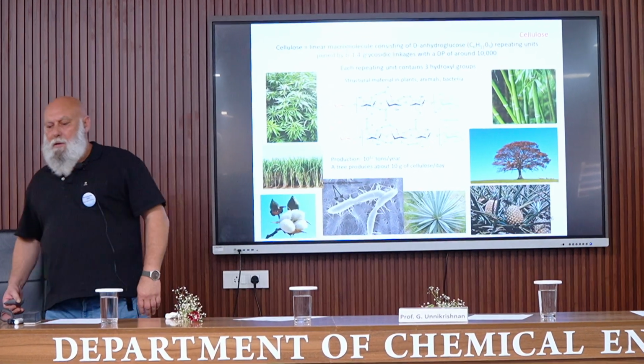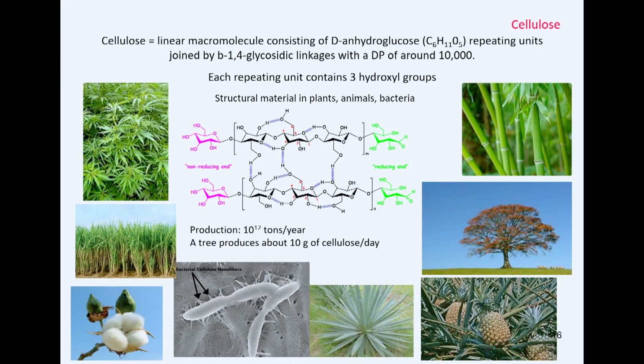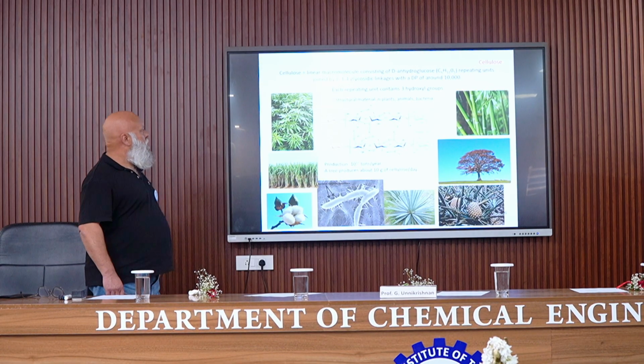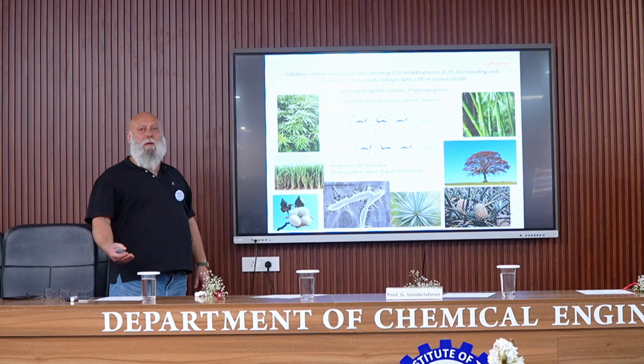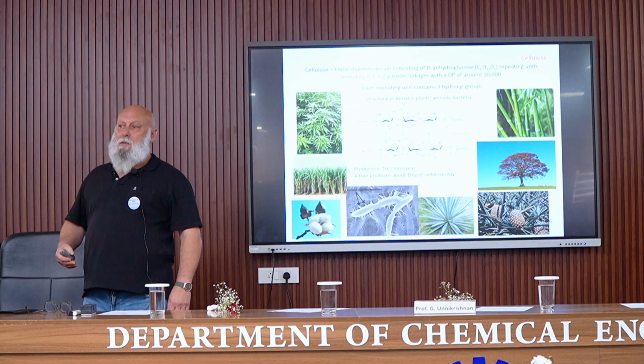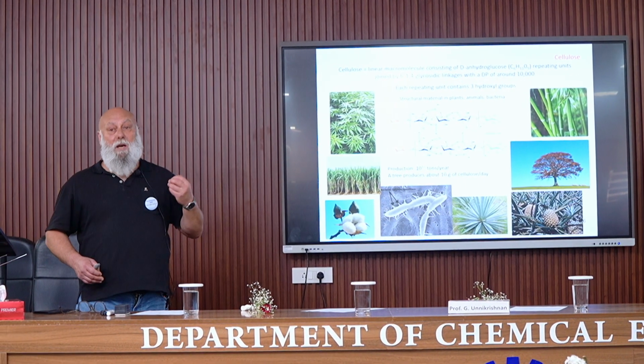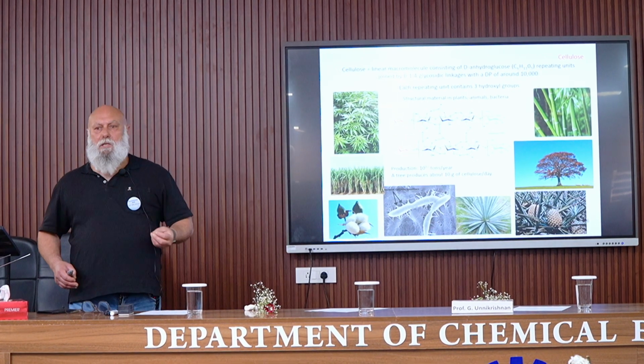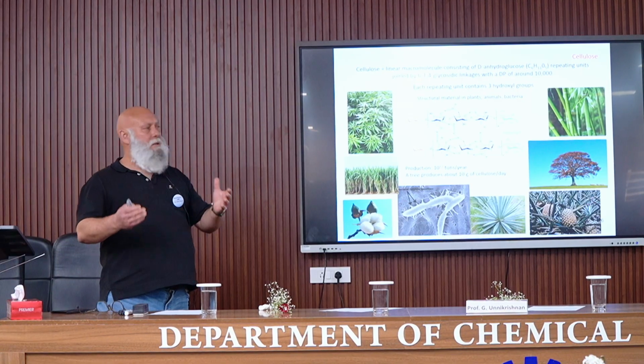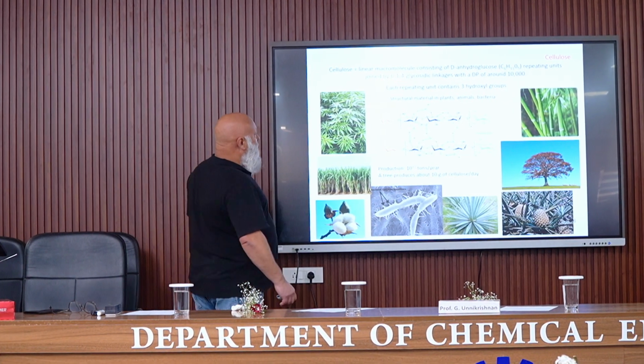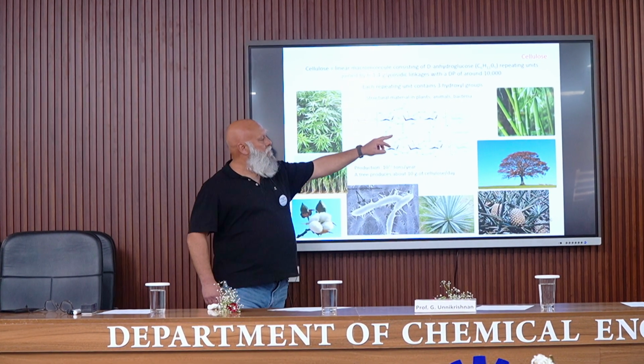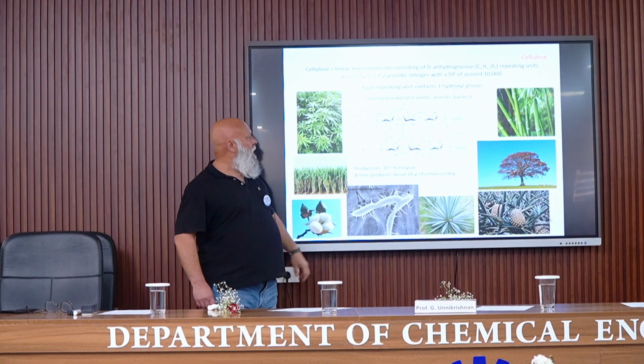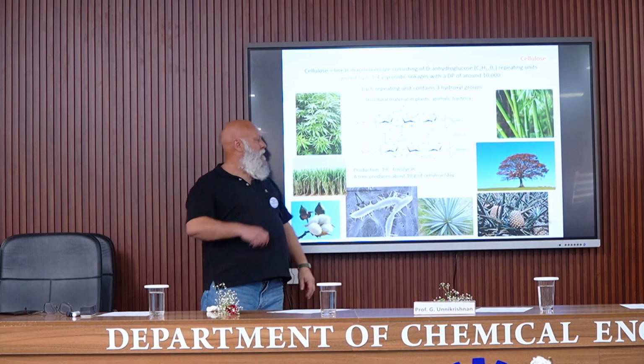So, we have three main components. Cellulose: you can see the chemical structure of cellulose here. It's a linear macromolecule, which is composed of this monomer unit. The DP is very high, generally around 10,000, but it is difficult to determine because the first step to determine the molecular weight or the degree of polymerization of cellulose is to extract cellulose from natural fiber. And this extraction process generally degrades the polymer, so it decreases the molecular weight. You can see also on these molecules there are two different ends: what is called a non-reducing end and a reducing end, that we'll discuss later.